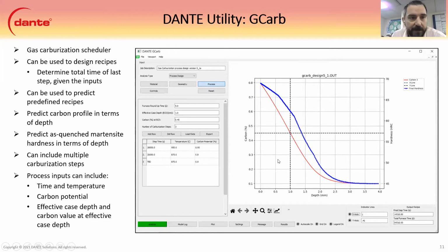GCarb works pretty much a similar way, only you're not going to use boost diffuse schedules. You're going to get time, temperature, and a hold for the carbon potential. So it's a scheduler. It can be used to design recipes. So here we see we define 2 steps, and then we say the third one is to be determined for how long it'll take. And then we define temperature and carbon potential at those steps.